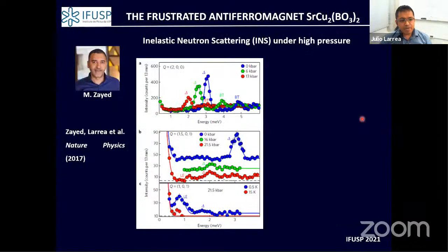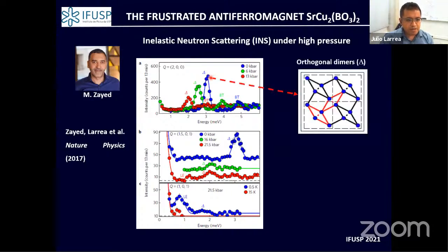Among the different experiments that have been done, and also theoretical predictions, the most suitable for this talk is to present the inelastic neutron scattering experiment under high pressure, published some years ago by a group when I was still in Lausanne. Neutron scattering is of course very sensitive to magnetic excitations, so it can simply measure the gap that separates the singlet state from the triplet state, okay?